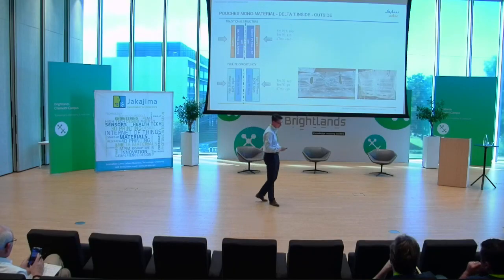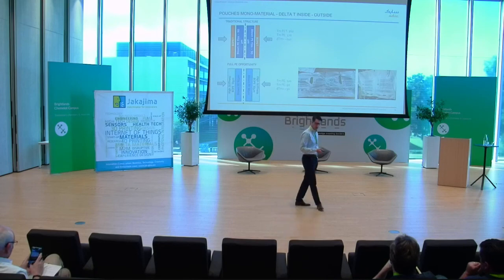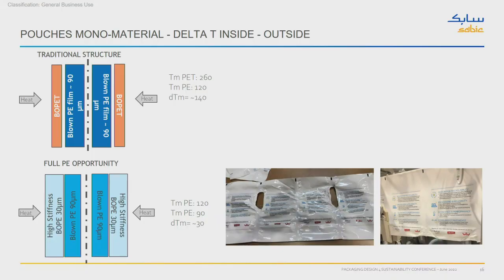If you then think, okay, I used to have my polyester laminate against the blown PE, everything is fine. I just translate that back into an oriented polyethylene with my same blown PE. But then you see, I have holes in the film when I run this on a packaging machine. So, actual testing, sealing of a film. There's a heat seal bar on top of that. You seal the film, but you seal through the film, and that's the thing you don't want.